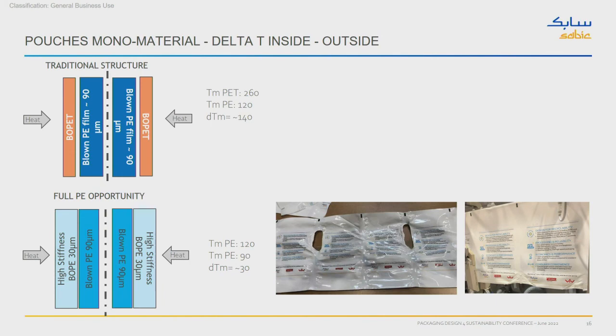So if you apply the heat on the outside, the polyester protects the rest of the film. Then you melt on the inside of the film, these dotted lines here. And then in principle you seal the blue layers on top of each other in the traditional way. If you change that to polyethylenes, BOPE against the same blown PE, then this is what we see. And it's also logical, because the melting point of the outside of the film is roughly 120 degrees, inside 90 degrees, which gives you, I don't know, a delta T of 30 degrees. So your processing window is much narrower.